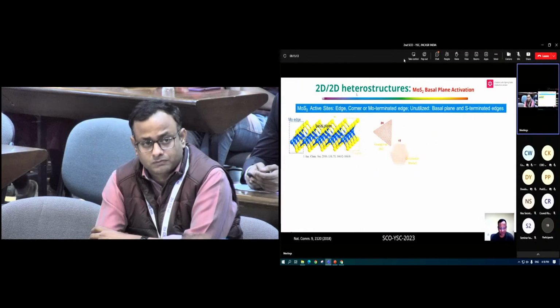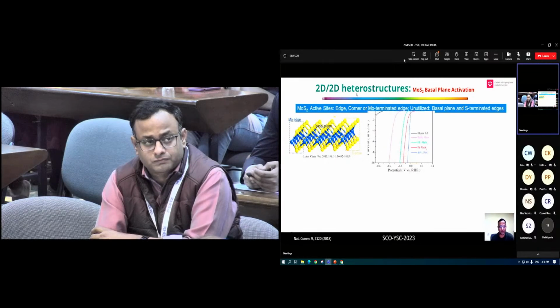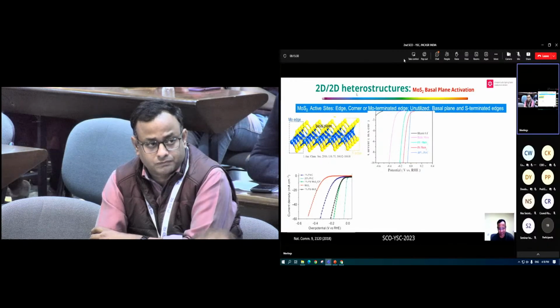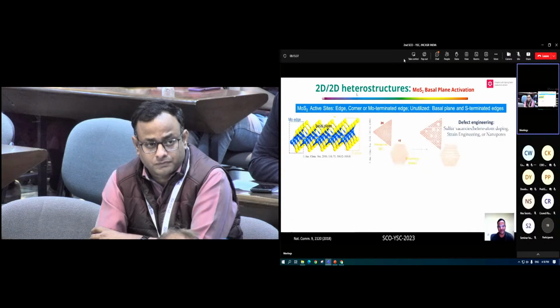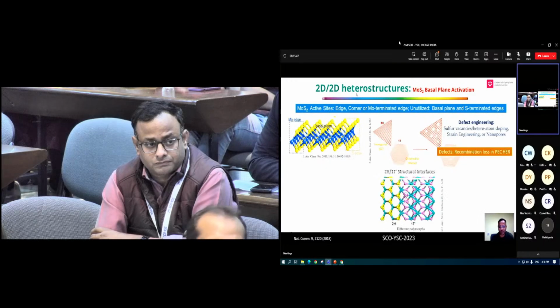So coming to the first part, MoS2 has been theoretically predicted as an alternative to platinum, but because of the low activity of the basal plane, only the edge sites and corner sites of MoS2 are active, so the efficiency of that material is not as theoretically predicted. People are trying to modify it with platinum, palladium, but that is not the solution overall when you are talking about commercial scale. Then defect engineering comes into the picture, but once you do defect engineering, it is very harmful for recombination in PEC. So that is not the solution for PEC.